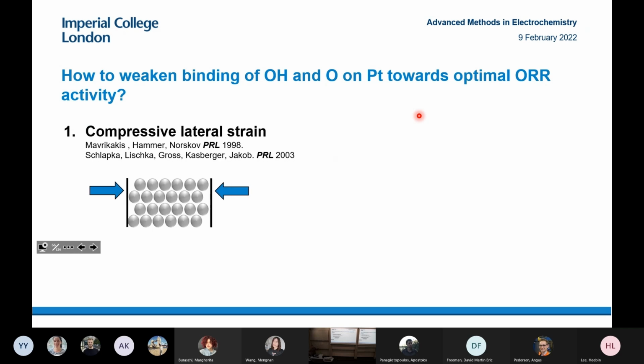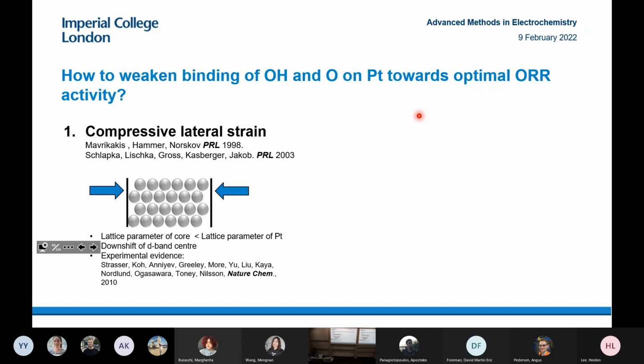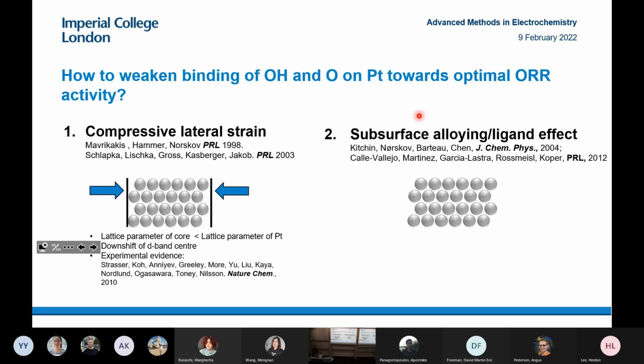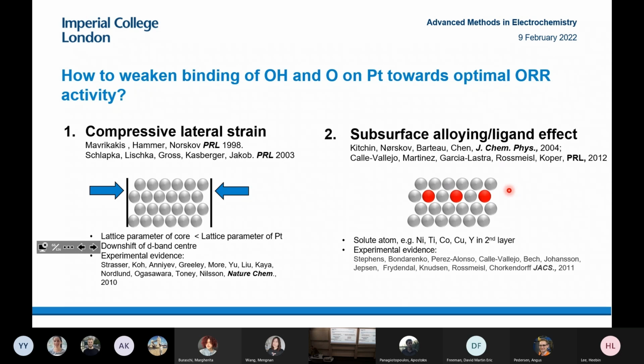Essentially, strain effect is when you apply a compressive lateral strain onto the surface. For example, Peter Strasser showed this to be the case when you make platinum copper nanoparticles. You have a very thick platinum layer. There's no ligand effect because you have a very thick layer, but because copper is smaller than platinum, there's a lateral compressive strain to the surface. And this weakens binding to oxygen. The other effect is one I've already discussed, which is the ligand effect. This is more short range. It's only from nearest neighbors of the platinum surface atoms. So this is when you have copper or another metal in the second surface layer.